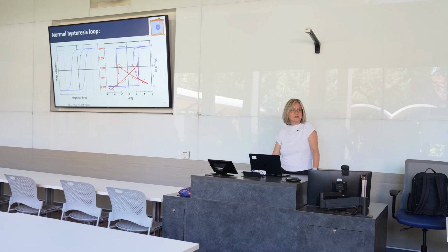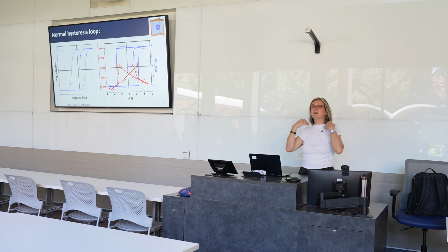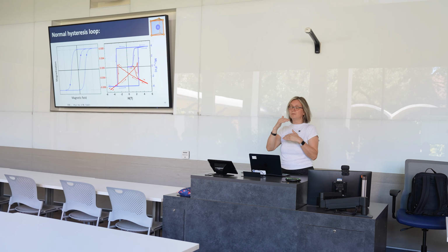Well, why does that happen? Well, we're trying to understand that by looking at the temperature dependence of these magnetization isotherms and of the resistivity isotherms. So it turns out that in this ordered 2x2 superstructure, the moments are parallel to the c direction, so they're perpendicular to the planes, and they all switch at the same time, giving rise to this very sharp switching.